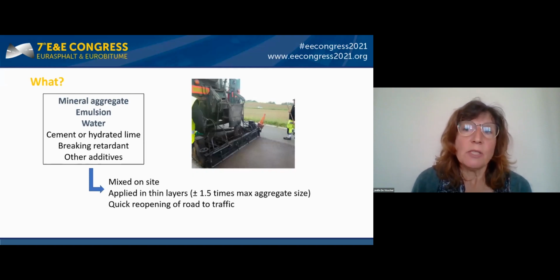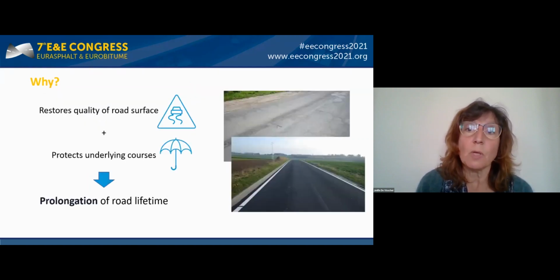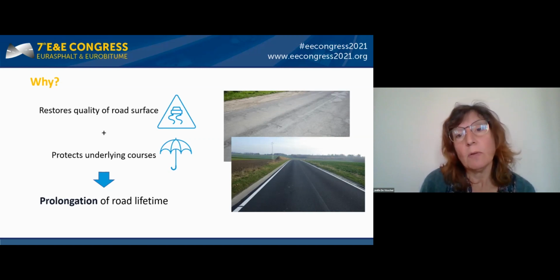Slurries, as you probably know, are mixtures of at least three components: mineral aggregate, bitumen emulsion, and water. Very often there's also a small quantity of active filler, a dope to retard the breaking process, and possibly other additives like pigment for coloration or fibers for strengthening. The mix is prepared on site and then immediately spread, and usually after 1 hour the road can be reopened to traffic. The result is then a new and smooth surface with restored skid resistance, and by restoring the waterproofing, the underlying structure is also protected against further deterioration. So it's clear that preserving the condition of the road using such a cost-effective technology is on the long term much more sustainable than, for example, regular milling and repaving.